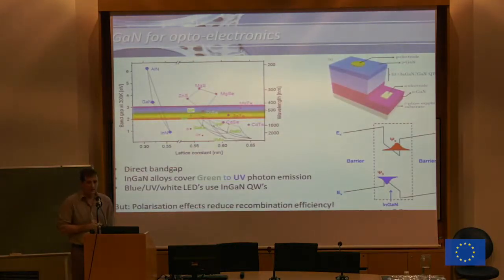Now, why is gallium nitride such a good choice for optoelectronics to start? One of the main aspects is that gallium nitride is not just one material, but in fact it is a complete family of materials. You can see it here. You don't only have gallium nitride. You can add aluminium, really increase the band gap up to 6.2 electron volt. And as was explained yesterday, that gives you this very huge critical electrical field. So it gives you very good properties for power.